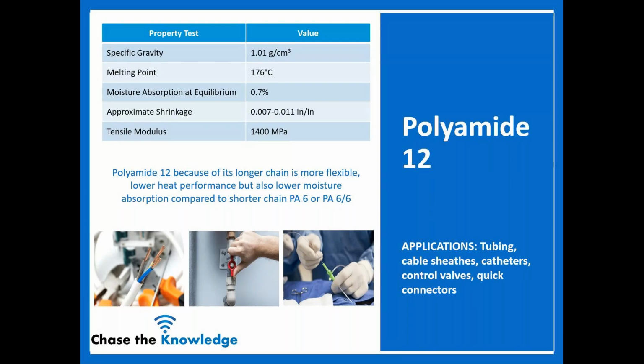It is a longer chain, making it more flexible, but it has lower heat performance because of that, as we mentioned, but it also has lower moisture absorption than your shorter chain 6 and 6,6. And so you'll notice as we go through, tables will be there, but your moisture absorption being at 0.7. And then I provided shrinkage as well as tensile modulus. So you can get an idea when we say that it's a little more flexible, the stiffness will be lower.